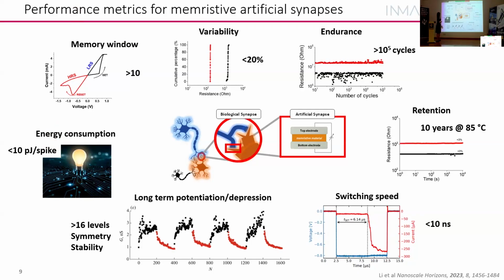About 10 is large enough. What else? Low variability. This refers to cycle to cycle in the same device or device to device. Strong endurance. So it means that we can cycle them for more than 10 to the 5 times, lots of cycles, and it has to behave the same. Long retention, very fast switching speed, so less than 10 nanoseconds, and that we can do this potentiation and depression with lots of states. And finally, we want to reduce the energy, so each of these operations should have a very low energy consumption. Okay, so this is our ideal device. Then it's very difficult to reach all these characteristics.